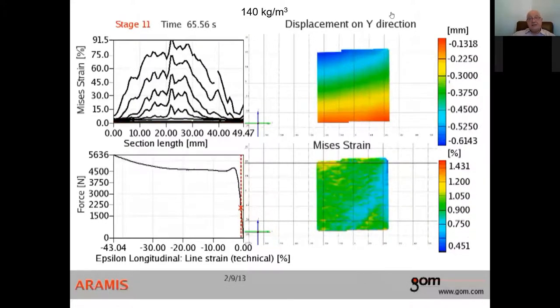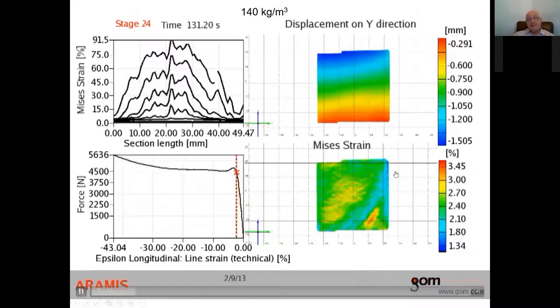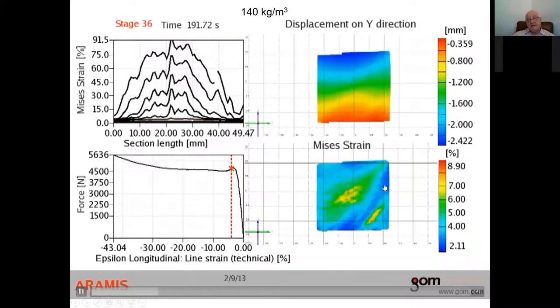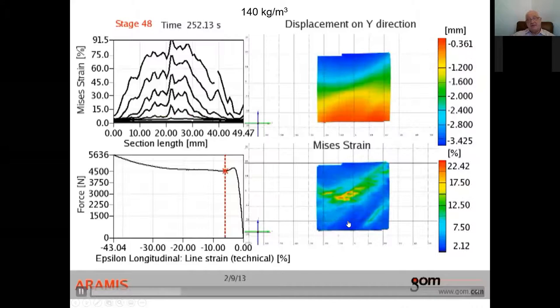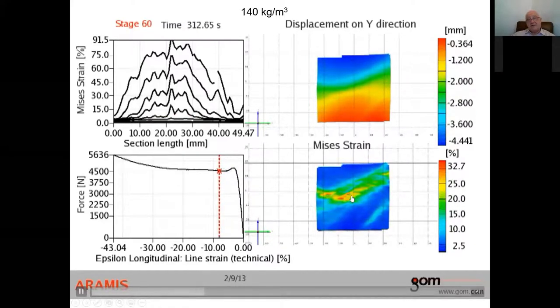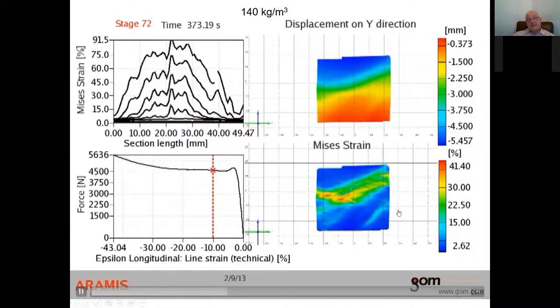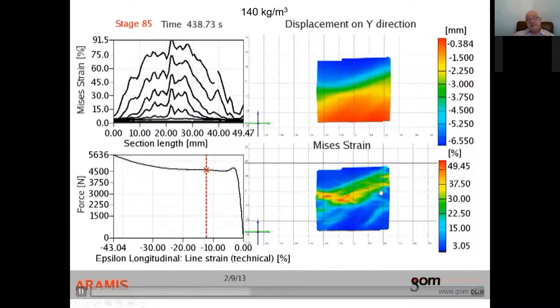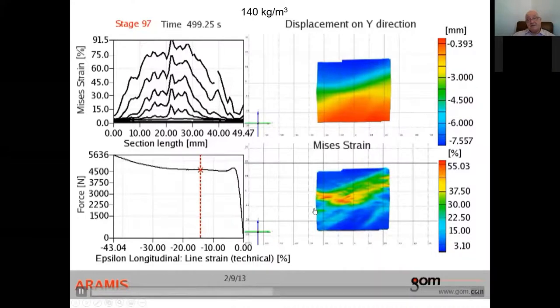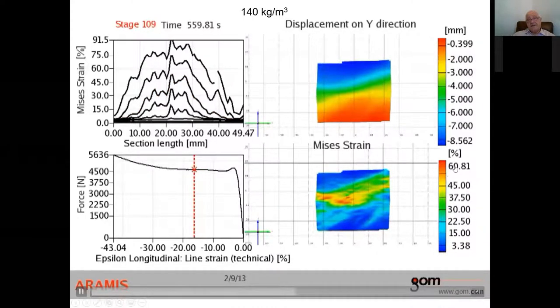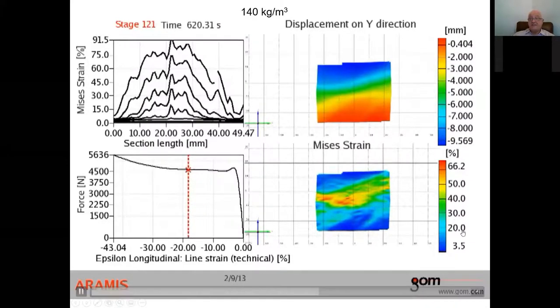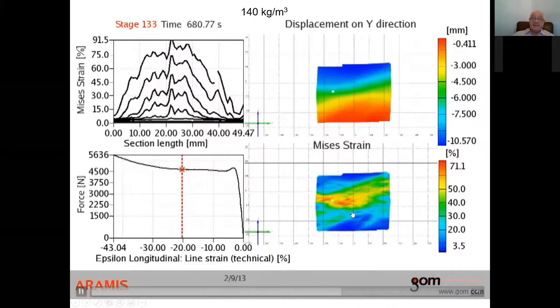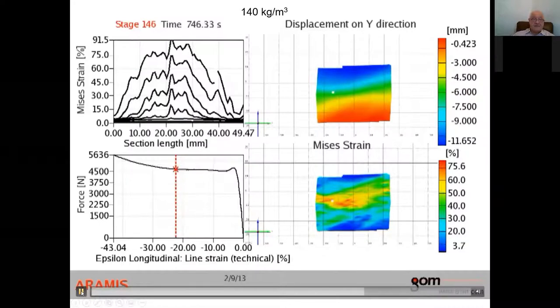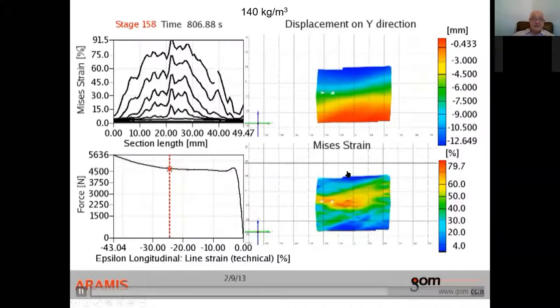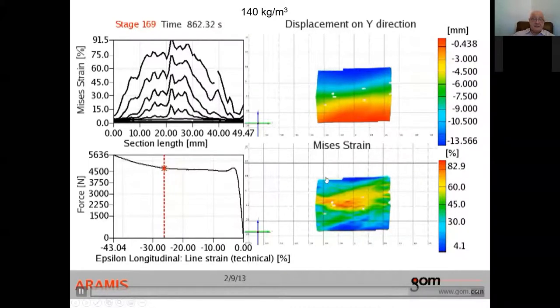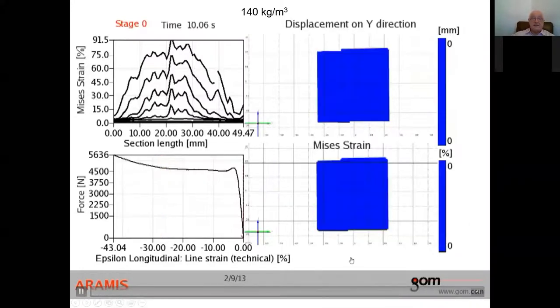So change density. And you can see already the deformation band here is coming in this direction, more like 45 degrees, like shearing. And then, as loading is applied, this deformation band goes horizontal. And the local value of the strain is much higher, 60% compared to less than 2%. And of course, this shows once again that the damage and this type of deformation bands are moving quite interestingly.